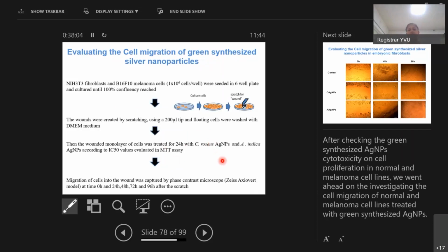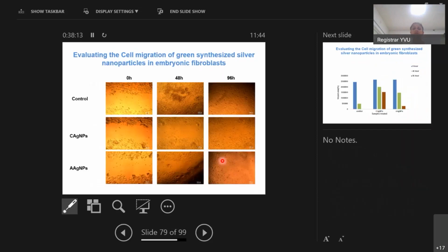This is the protocol I used for cell migration analysis of green synthesized silver nanoparticles. This is the scratch assay protocol. This is the cell migration analysis in mouse embryonic fibroblasts at different time points: 0 hours, 48 hours, and 96 hours. This is the control group, and these are the CA-GNPs and AA-GNPs groups. At 0 hours, cell migration was not observed. At 96 hours, cell migration was observed. These green synthesized silver nanoparticles enhance the cell migration activity in the normal mouse embryonic fibroblast cell line.